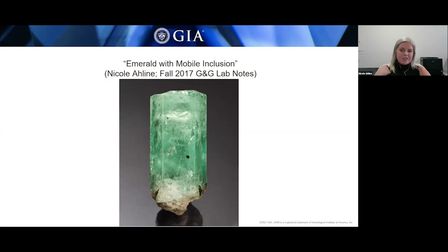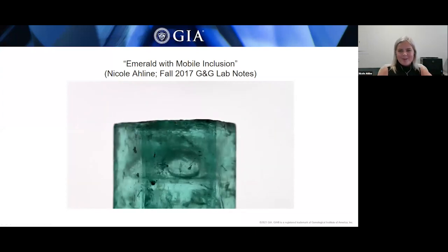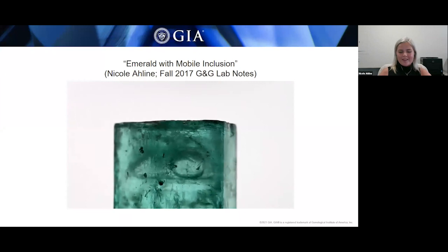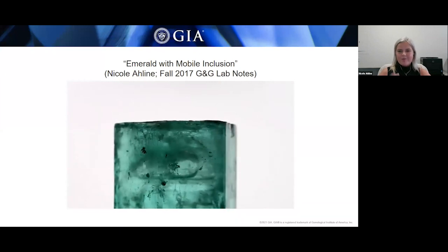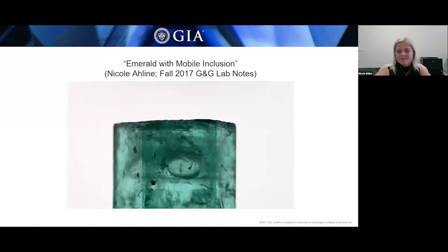And so the origin was determined to be Colombian, and that was supported by the jagged 3-phase inclusions, as well as some pyrite and calcite present. And so here we can see the bubble moving, which is super cool. And it was actually quite large. The bubble itself measured about 4 by 3 millimeters.